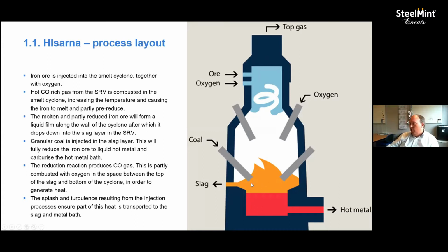In this slag layer we inject coal, powder coal, and this coal, this carbon, completes the final reduction stages. So it turns the liquid FeO into a liquid iron, with carbon dissolved in it. It turns the oxygen together with the coal into CO, and all the other components in the iron ore pretty much, that's all silicates, aluminates, they become part of the slag. To condition the slag, we do inject a little bit of lime with the coal. All other fluxes we inject together with the iron ore, so limestone and dolomite we inject with the iron ore.